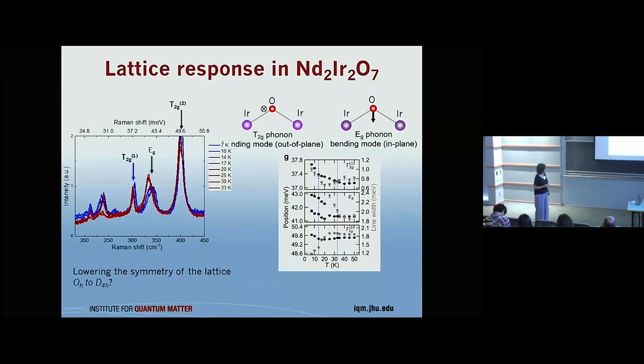Basically, the triply degenerate and doubly degenerate phonons broaden as we introduce the iridium order, and the Eg splits into two bands as neodymium order kicks in. In principle, this would be in agreement with a lowering of the symmetry of the lattice, if you look at the symmetry of the phonons, from point group Oh to D4h. So there could be some symmetry element lost. Weirdly, the triply degenerate phonons change much less than this doubly degenerate phonon, but it could also be a question of the magneto-elastic coupling coefficient. This is the same as observed in the europium iridate, but this is under discussion.